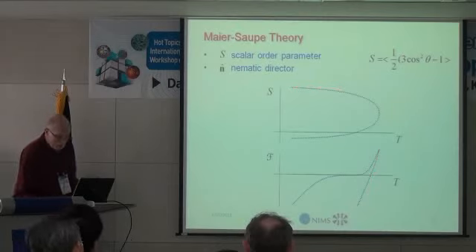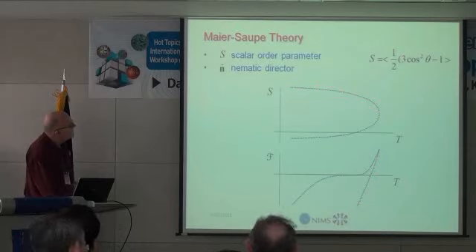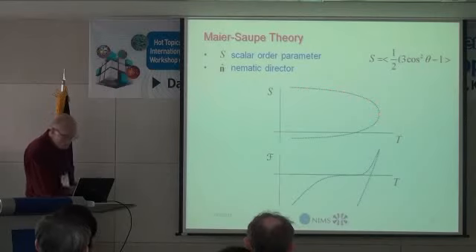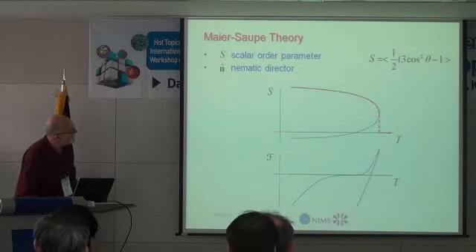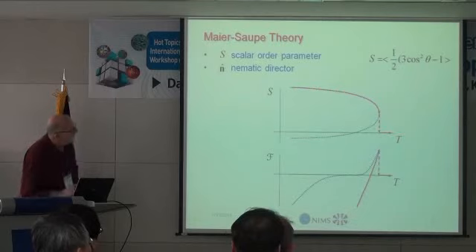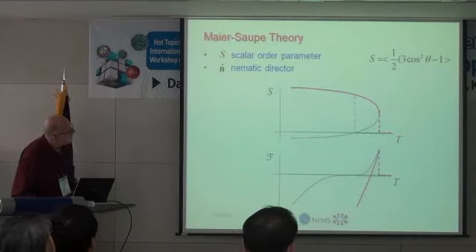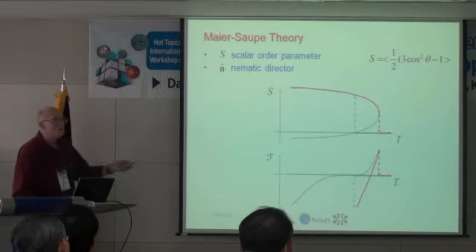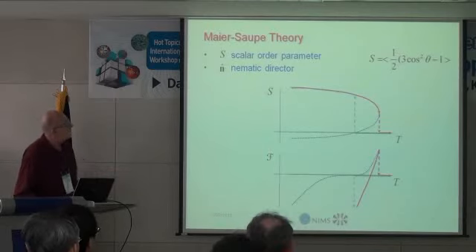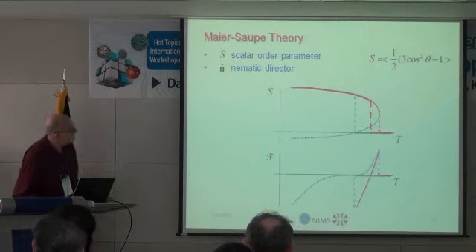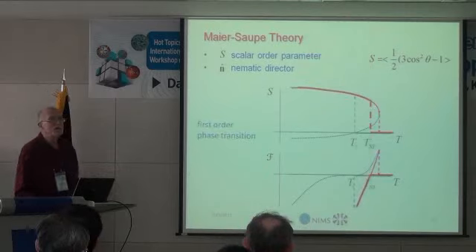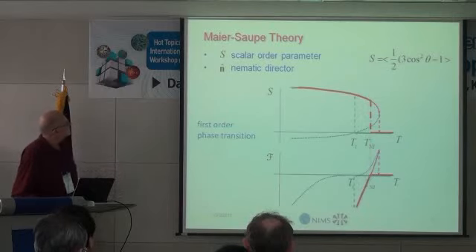And then if you were to heat up a sample, it would move along here, and then at this point it would fall down to the isotropic solution. On the other hand, if you were cooling the material, it would do the other thing. And so one can superheat and supercool these materials, and the actual phase transition occurs at that point there. So this is the phase behavior, typical first order phase transition.